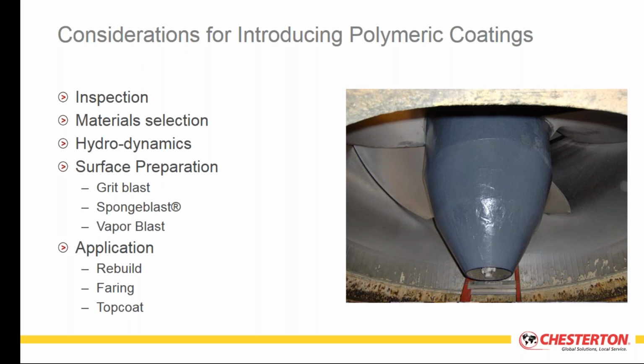The largest investment in time and money of any polymeric coating application is surface preparation and application. My experience says it's usually somewhere between 75 and 80% of the cost of the job. But when done properly and successfully, the coating systems have the best opportunity to perform, and they become quite economical because you can affect these repairs quickly, in a matter of days as opposed to weeks with more traditional methods, and there's nowhere near the amount of cost involved in rigging and heat stress relieving, both pre and post. So it's a more effective approach.